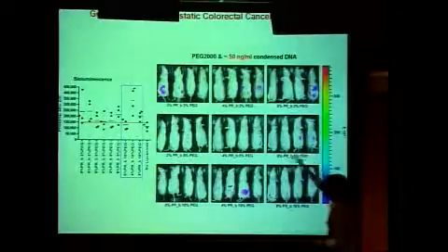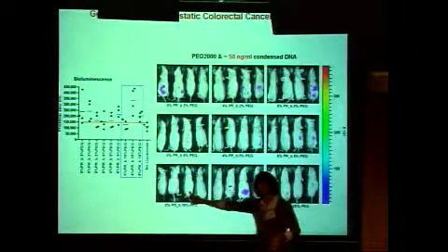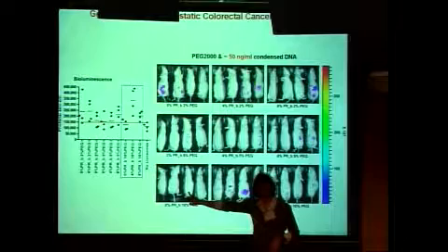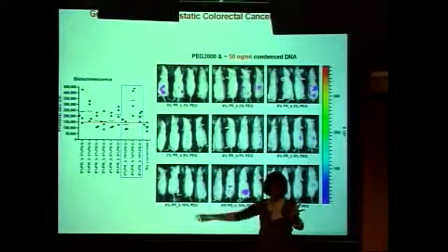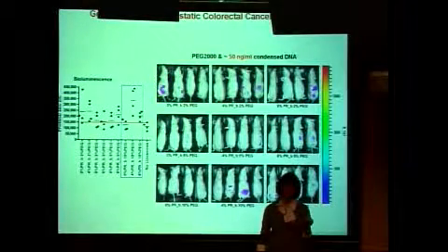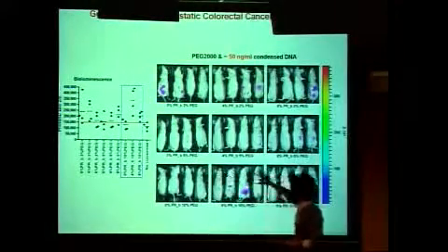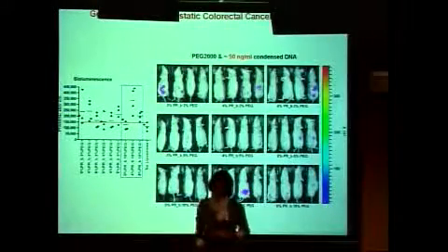The minute I start increasing the polymer and the repulsion, now we see that if I don't have the targeting, I don't have any delivery. The nanoparticles will probably go there just because of their size, but they will not get entry to the cell. They will not go inside. So then when I start incorporating the peptide, then we see a significant improvement.